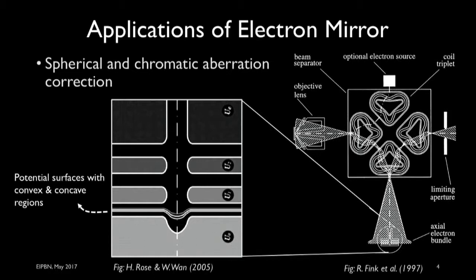These positive and negative curvatures in turn produce positive and negative spherical and chromatic aberration coefficients. With this, we can actually counteract the aberration that was produced by the electron lenses prior to this mirror. And then when the beam is corrected, we can reflect it back up, and then it could be used for microscopy, free of the aberrations to an extent.